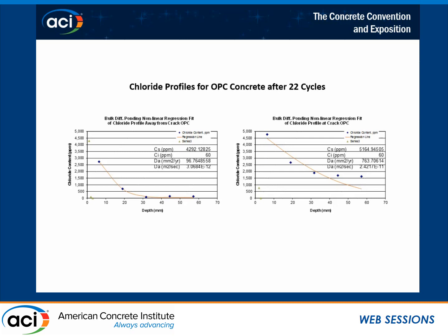Looking at the chloride contents, since they have a very short wet cycle, they're wet most of the time, half the time, and it's really not drying that much. We figured we'd just plot them on points, on curves, and try to fit them to a bulk apparent diffusion. So it's not 100% accurate, but it's good for illustrative purposes. These were not quite as long: this is 22 cycles, which is 44 weeks, versus what I showed you before, which was a 2-year study. But you can see how the chloride's coming down in time, fitting kind of like a diffusion curve.